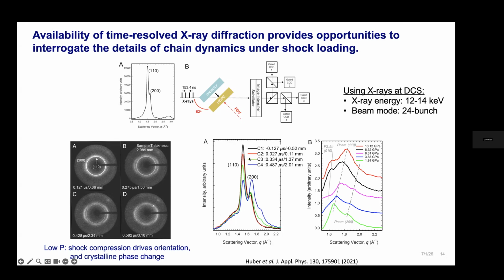Basically, the first figure, figure A, shows that at the time we had 4 cameras. This was some of the early work at DCS. We had 4 cameras taking 4 images. And what you can see is that there is, in fact, an evolution of the wave in time, or evolution of the diffraction pattern, as the wave goes through the sample to a depth of about 2 millimeters.